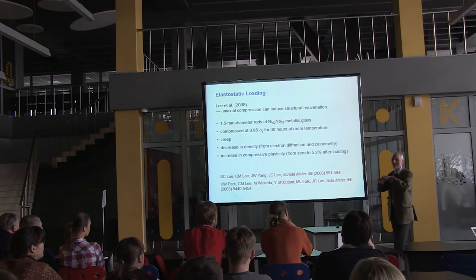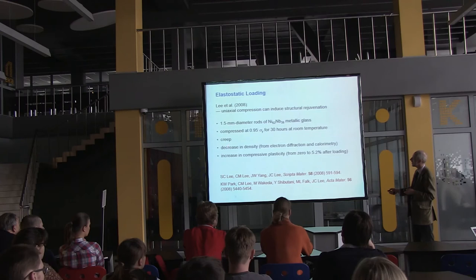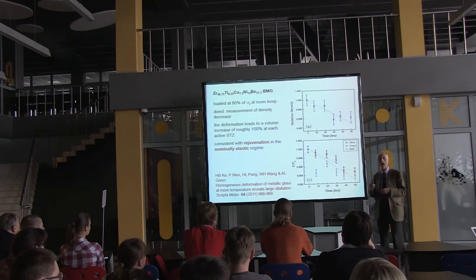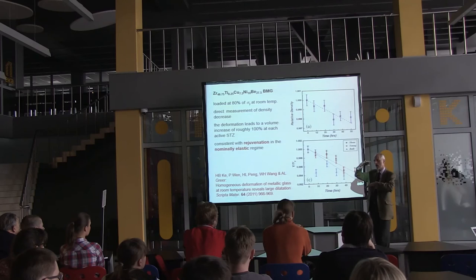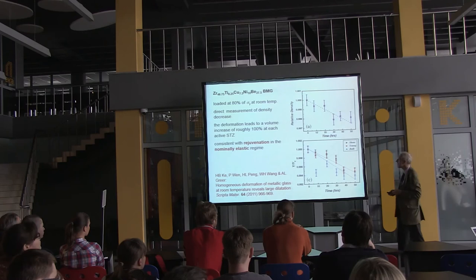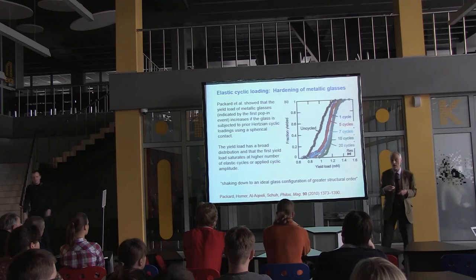The experiment concluded there had to be a decrease in density. We later did related experiments at 80% of the yield stress with a direct density measurement — the volume goes up as a result of compression. Because it is not hydrostatic — only one direction — you get some creep, meaning shear, and the shearing gives an increase in volume. That increase in volume changes the properties of the material and makes it more plastic even within the elastic range.